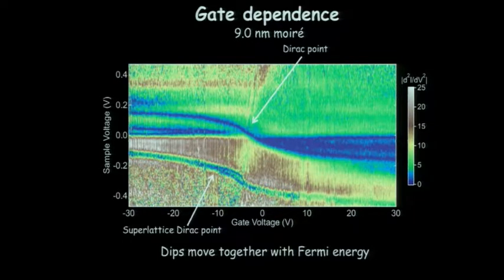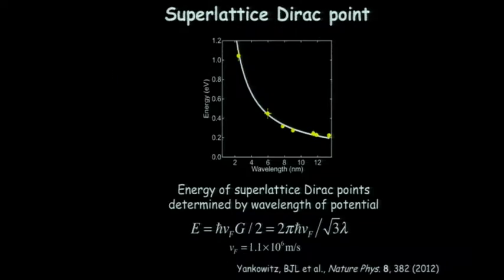And from this, you can read off the energy of this dip. So this one is like 0.25 electron volts or 0.3 electron volts away. And so from that, and this 9 nanometer Moiré, those two pieces of information are all you need to know about for the wave vector. And so we plotted that energy as a function of wavelength or inverse of the wave vector, and we found this nice 1 over wavelength. It's linear with the wave vector.